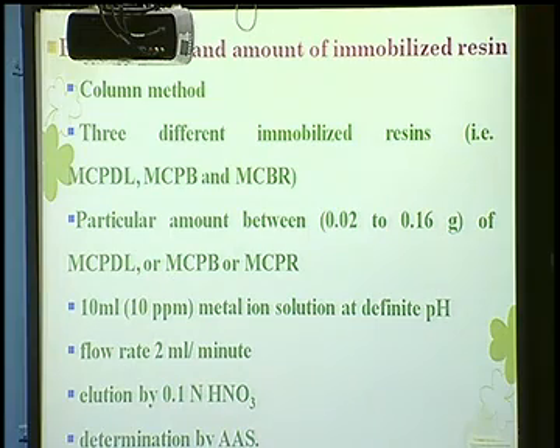For this, we have used the column method, 3 different immobilized resins, that is Calotropis procera bark, root, and dry latex. The amount of the latex, that is from 0.02 to 0.16 gram of modified resins. Flow rate was 2 ml per minute, and elution was carried out by 0.1 normal HNO3.